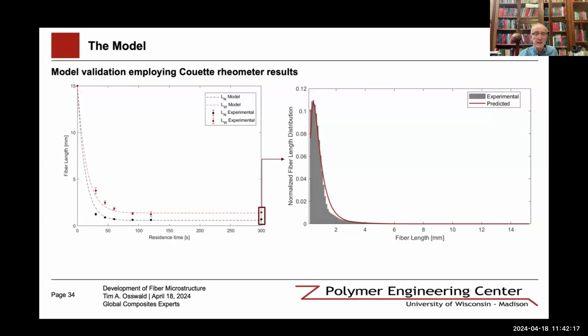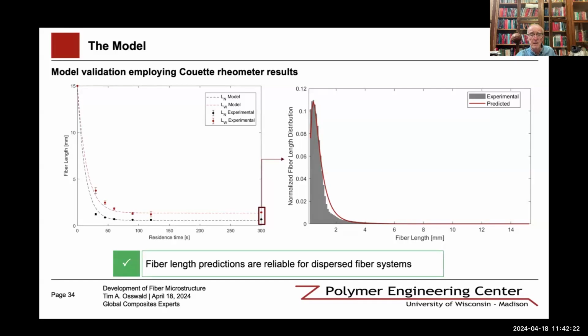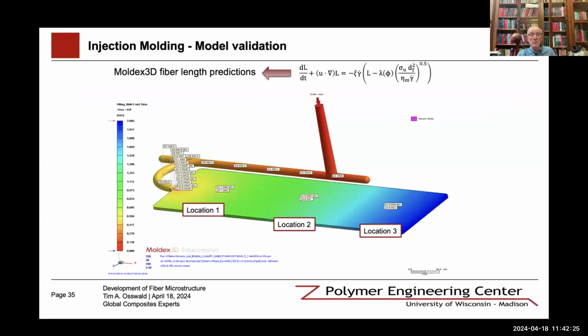So the fiber length model, or fiber attrition model, was then implemented into Moldex3D. And it was tested with a simple plate. You can see the plate right here. So there are three locations 1, 2, and 3. For that, of course, we need the length distribution after the plasticating unit. So we start out, we do a purge of the injection molding machine, and in that purge, we measure the length distribution, and we use that as an input to Moldex3D.